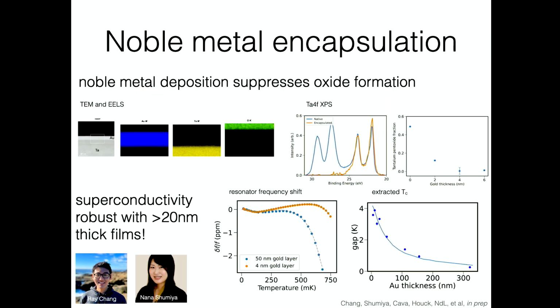Okay, so let me just show you, because I think it's always important to show new stuff, some of the things that we've been working on. So we want to get rid of the surface oxide. A natural strategy to try is to just not have a surface oxide. And the metals that do not form surface oxide are the noble metals. So think gold, palladium, platinum. The problem is that none of those things superconduct. But one thing that I can do is put a very thin film of gold on top of the tantalum before I break vacuum and form an oxide, and suppress the oxide formation.